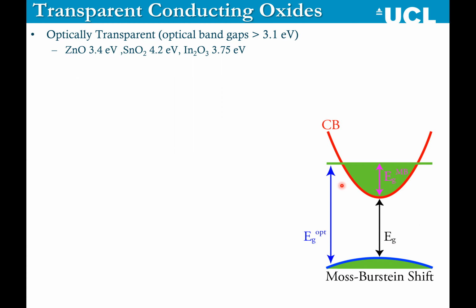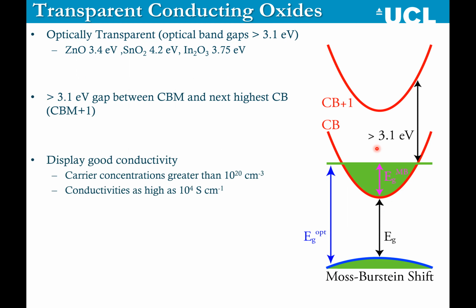Of course, there's issues with this because now you have electrons in the bottom of your conduction band, and as light hits your material, it could excite these electrons into other low-lying unoccupied states. So the next caveat is that we normally need to have a large separation between the conduction band and the conduction band +1, or the next lowest unoccupied state. And typically, these systems display very good conductivity, so carrier concentrations greater than 10 to the 20 per centimeter cubed, and conductivity is as high as 10 to the 4 Siemens per centimeter.